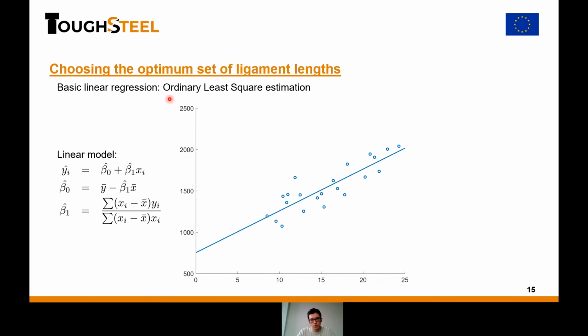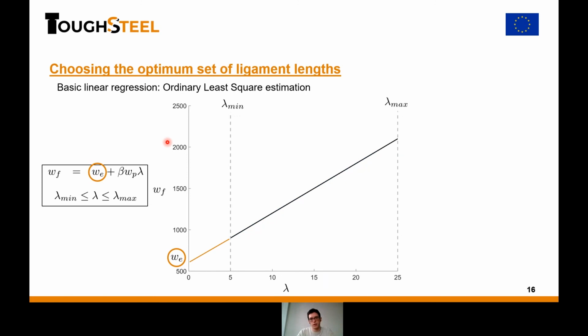And so the OLS estimation, ordinary least square estimation, is the most basic way to do linear regression. It is basically to minimize the square of the distance between the straight line and your data points. And this translates to this formula. So this is a very classic way to do linear regression. And in the case of the essential work of fracture, it's exactly this. So we have your total work, that is the sum of two contributions: one constant term, that is the essential work of fracture, and a term that is dependent on the ligament length, times a parameter, the non-essential work of fracture, and a shape factor beta. But the important thing is that the ligament length is bounded by two values. Here I call them lambda min and lambda max.